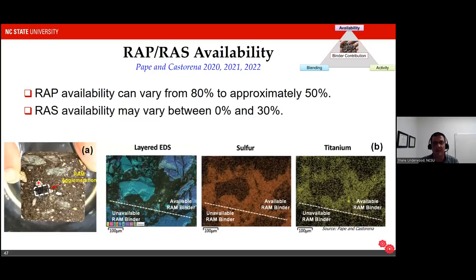I'm not getting into the specific details, but what they have concluded is that the availability for RAP varies quite a bit from one stockpile to the other. Up to 80% in some cases. Those are cases where it's really available, doing a lot of good in the mix, all the way down to 50%. And when it comes to RAS, they may actually get no benefit from the RAS at all. It might not be giving you any binder. None of the binder is available in the mix.